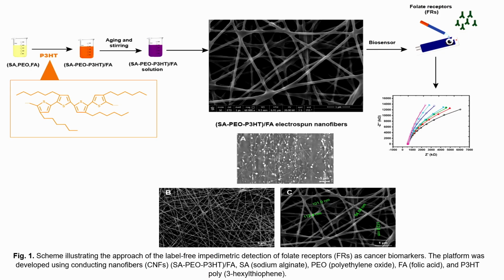We prepared our polymer solution from sodium alginate and polyethylene oxide with our biorecognition element, folic acid, in aqueous solution. After that, we added the P3HT and stirred until the color changed to purple, which confirmed the formation of nanoparticles due to the non-solvent aqueous medium. And we used the electrospinning technique to obtain our nanofibers.